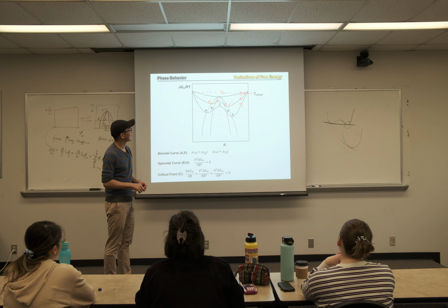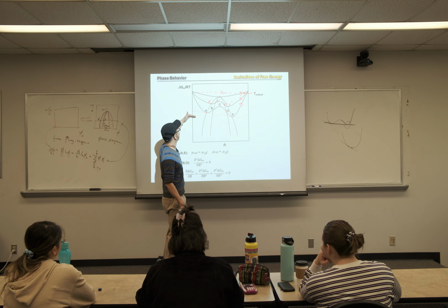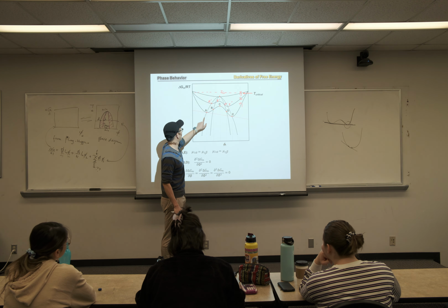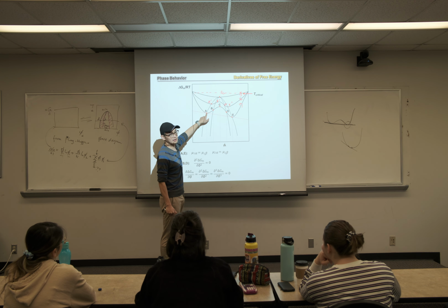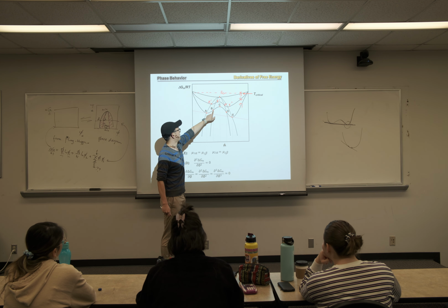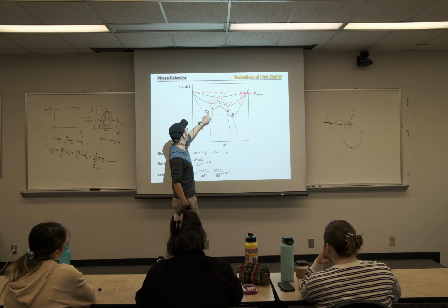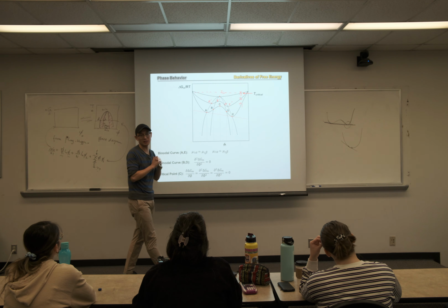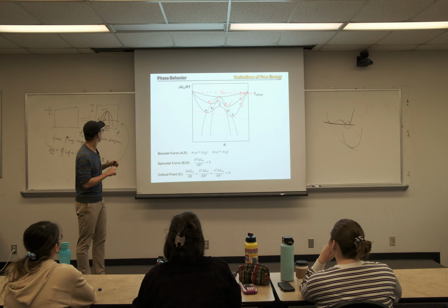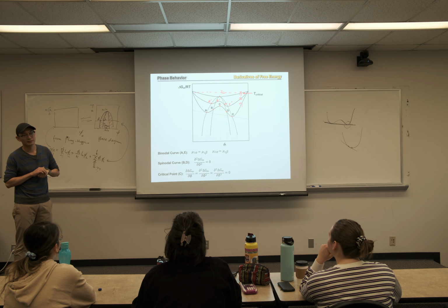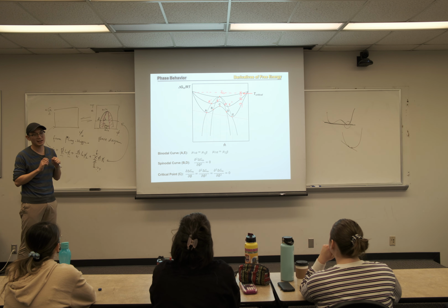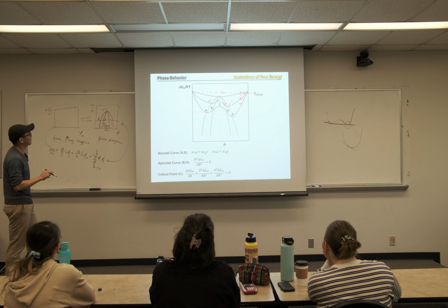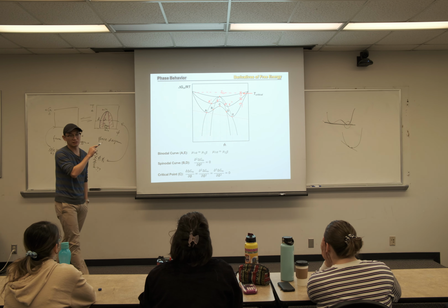Okay? So this corresponds, in the phase diagram, to how we get T as the axis, because you can see this would be defining the edge of metastable. This will define the unstable states. So if we pick those A prime, B prime, etc., we can construct the phase diagram. That's how these are linked. The trick is at each temperature, you will have a different delta G curve.